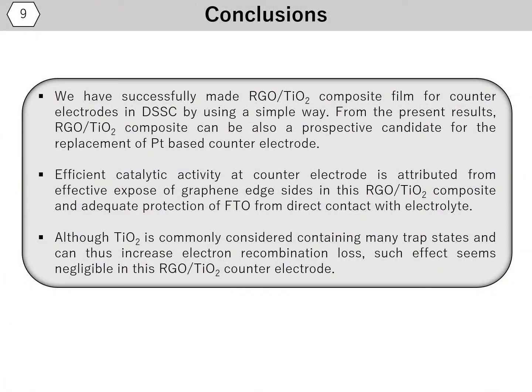We can conclude that we have successfully made RGO titanium dioxide composite film for counter electrode in dye-sensitized solar cell by using a simple way. From the present result, RGO titanium dioxide composite can be also a prospective candidate for the replacement of platinum-based counter electrode. Efficient catalytic activity at counter electrode is attributed to effective exposure of graphene edge site in this reduced graphene oxide titanium dioxide composite and adequate protection of FTO from direct contact with electrolyte. Although titanium dioxide is commonly considered containing many trap states and can thus increase electron recombination loss, such effects seem negligible in this reduced graphene oxide titanium dioxide counter electrode.